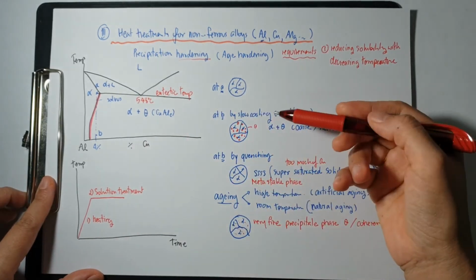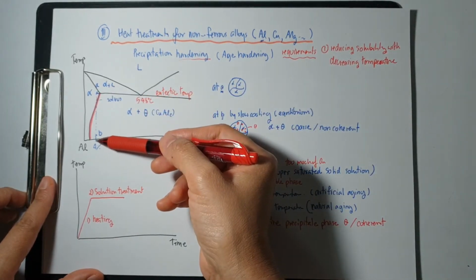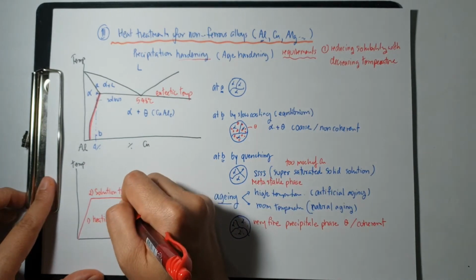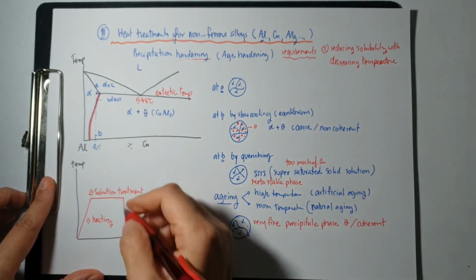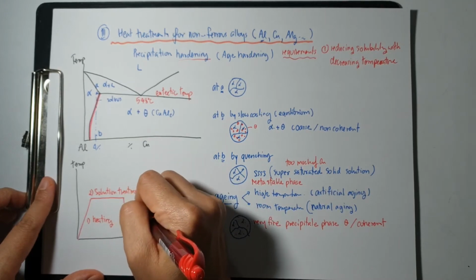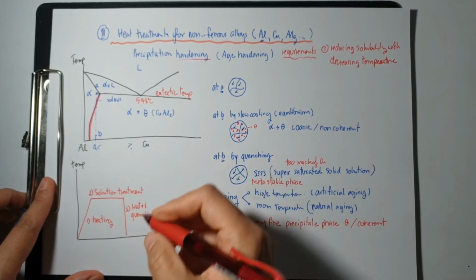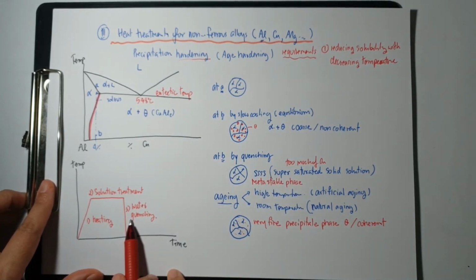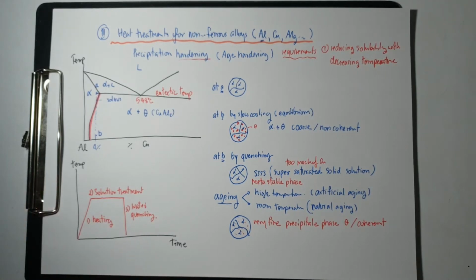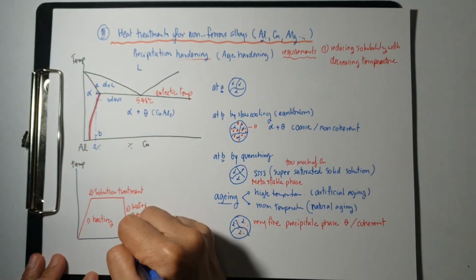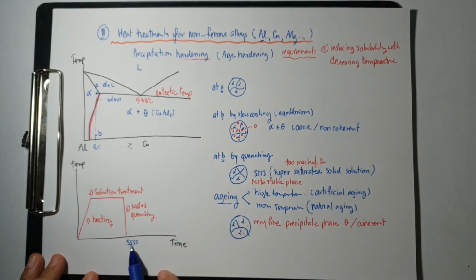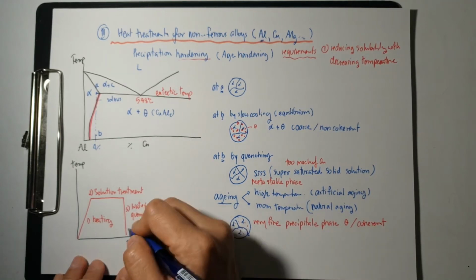Then we have to quench it down, not cooling slowly. When we apply quenching, we have the steep curve over here. Maybe water quenching. Right. Now when we cool the metal rapidly, it will give you the metastable phase of supersaturated solid solution, and now with time we change into the equilibrium phase by precipitate out the refined phase.